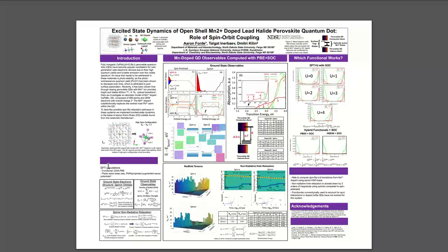Any questions or suggestions? I have a technical question. For your DFT plus U calculations, you only modify the U term, right? Did you play with the, I guess, J term? J, yeah. Well, I didn't do the calculation myself, the collaborator did. I would have to dig around in the directories that he did, but it doesn't seem like it because of the way he labeled the folders, it was U0, U1, U2, U3. So he must have kept J constant, unless he just changed it with each one, but I doubt it. Because it seems you need to find the combination of the U and J. Yes, you're correct. Okay.